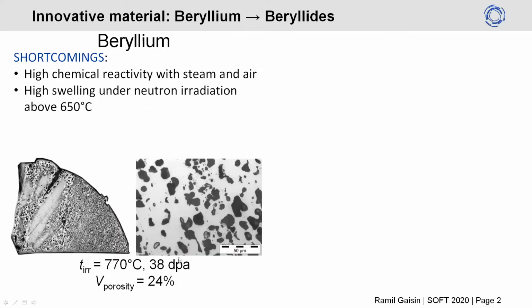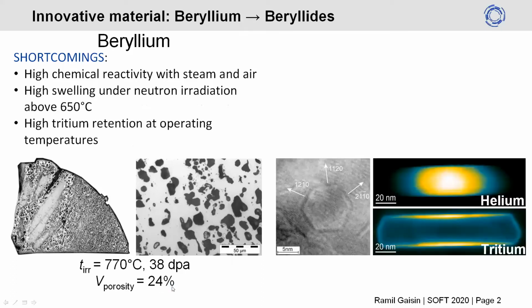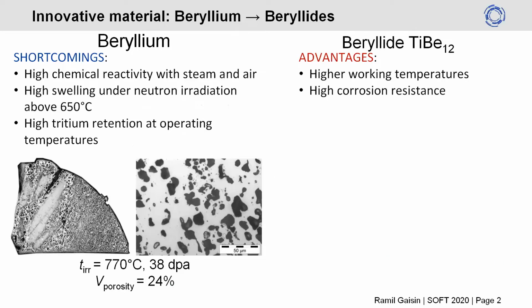Under neutron irradiation, beryllium swells intensively, forming a very high porosity. Beryllium also retains a lot of tritium on the surfaces of hexagonal-shaped bubbles during irradiation. But the addition of just one titanium atom to 12 beryllium atoms radically changes the structure and properties.